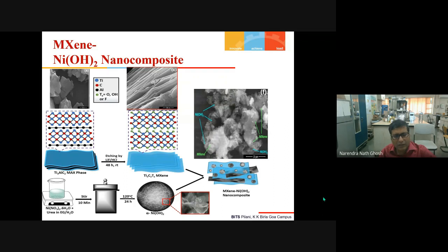Similarly, we make the flake-like structure of nickel hydroxide by treating nickel nitrate with urea, and this SEM shows that it's a flake. Then, as I told you earlier, during the reactions, either catalysis or electrochemical, that we are studying, we have seen that the layered structure of MXene collapses. To prevent that, we are trying to insert the flakes of nickel hydroxide within these layers. So what will happen is that it prevents the collapse of the layers.